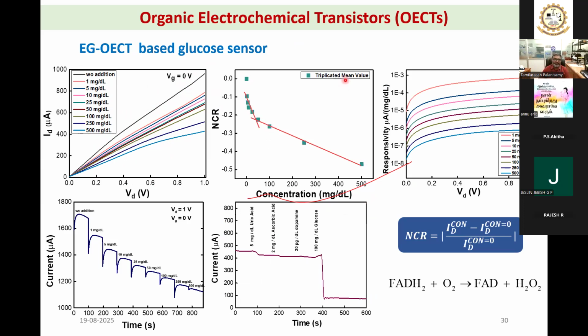Here you can see the difference. In the previous study, we have seen the sharp increase in response at lower concentration. Here also we are seeing the same trend, but the one big difference here is the response at the higher concentration. The higher concentration slope is comparably good when compared to the previous study. There we used a very small electrode, very small gate and very small channel. But here the channel and gate are relatively bigger. So we got a better response for higher concentration.